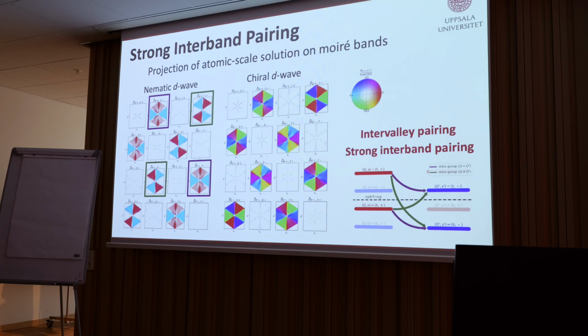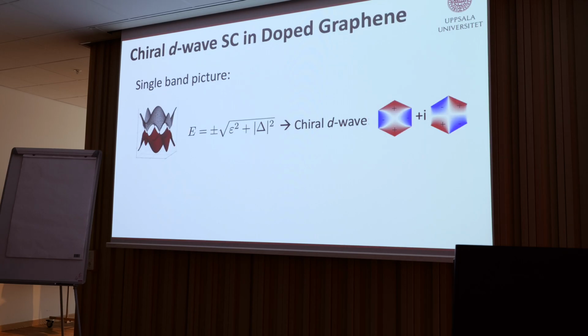So I have strong pairing between all the bands I can have in the Moiré structure within a zero momentum pairing regime. And that really means that this simple argument I had before, that I would get a chiral D-wave state, is not as simple in twisted bilayer graphene because I have very strong interband pairing. So this simplistic picture, let's have the chiral D-wave state because it's the only gapped state, that argument goes out the window. This is not relevant anymore with such strong interband pairing.